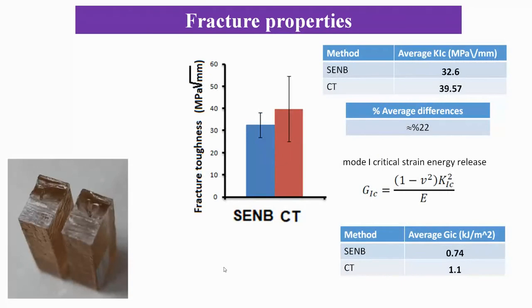In this slide, you see the comparison between fracture toughness values measured using the SENB test and the CT test. As you see, SENB gives an average value of 32.6 megapascal square root of millimeter for the fracture toughness, while the average value of mode 1 fracture toughness for the CT specimen is 39.57. Taking the standard deviation of both tests into consideration, you will see very close values for the fracture toughness. However, there is a difference of almost 22% between the average values of fracture toughness using these methods.